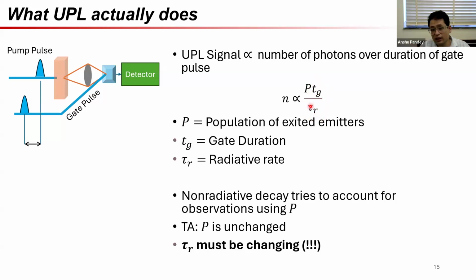This I'll prove by absurdity arguments. Because if we think that the radiative rate is infinite, or radiative lifetime, sorry, I don't mean rate, I mean lifetime. If the lifetime is infinitely long, then in that case, the sample will never really emit any photons. And this means that the signal would actually be zero. On the other hand, if this is very short, of the order of the gate pulse duration, I would get a very giant signal indeed. So the number of photons measured at any one point by this technique is actually dependent on the spontaneous emission rate of the sample as well, which makes it very distinct from both what TA and TCSPC are trying to do.